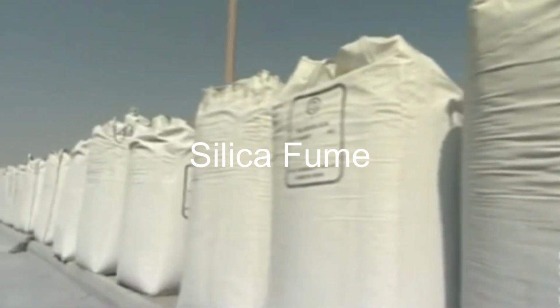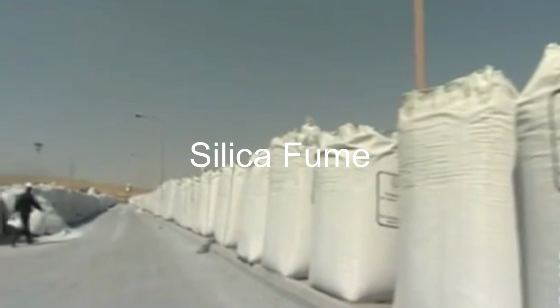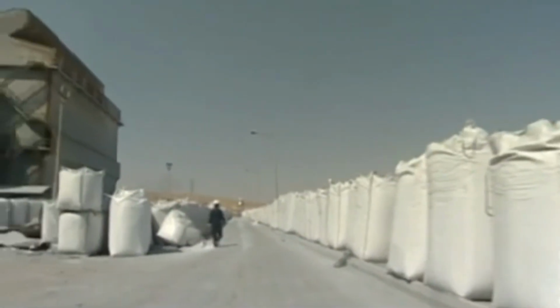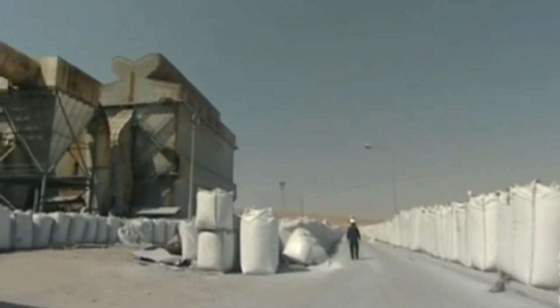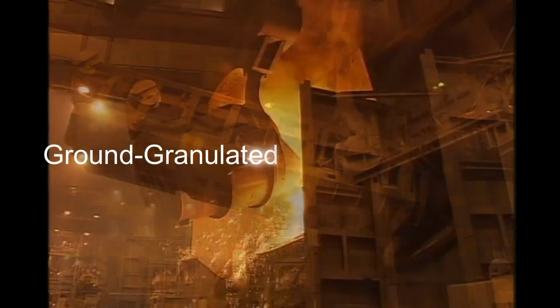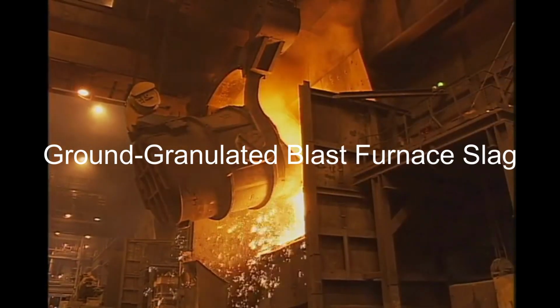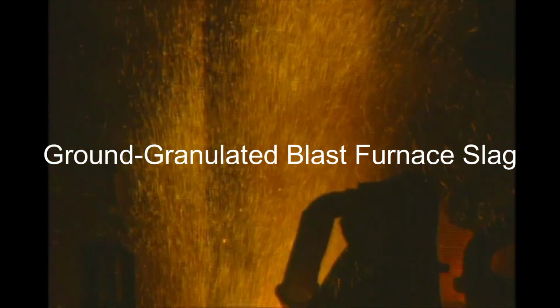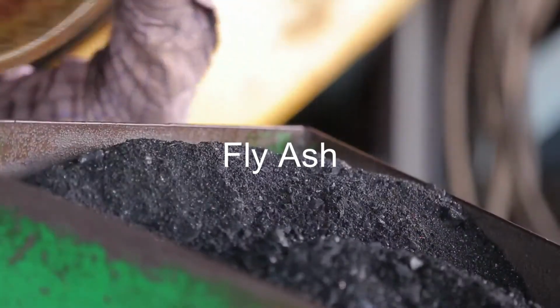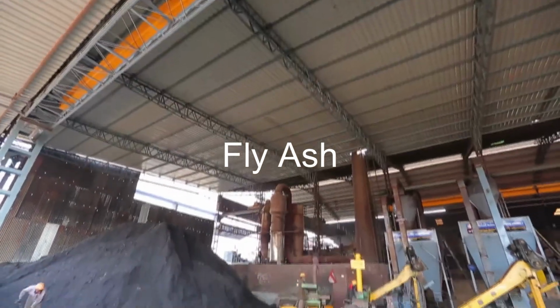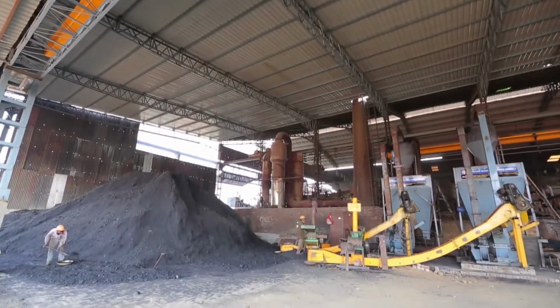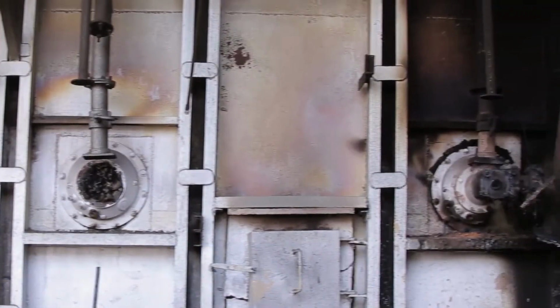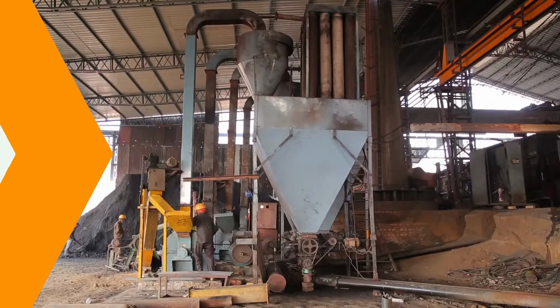Silica fume strongly reduces permeability and can increase strength. It often requires optimized admixtures and careful shrinkage and curing control. GGBFS lowers permeability and improves resistance to chloride and sulfate attack. Early age strength may develop more slowly. Fly ash improves workability, can reduce heat of hydration, and mitigates ASR. Early strength may decrease depending on type and replacement level.